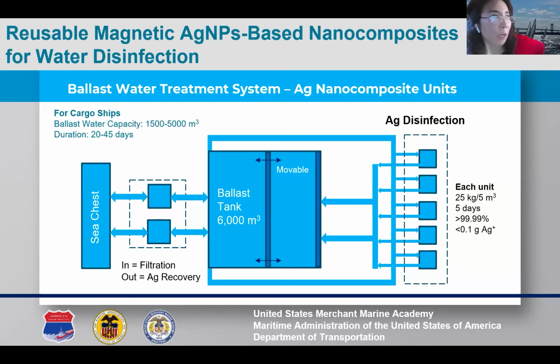Based on literature search, systems that undergo less of this kind of condensation process see no changes over 6 months in their performance or properties. So we believe our lifespan is very long as well. We took all that into consideration, how stable our system is, and we believe it's stable for a long time. Some studies didn't even go through as rigorous a process as we did, and they proved that their lifetimes can extend to 3 years without any sign of deterioration or degradation. So I think they're very stable.